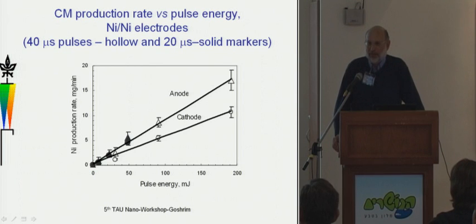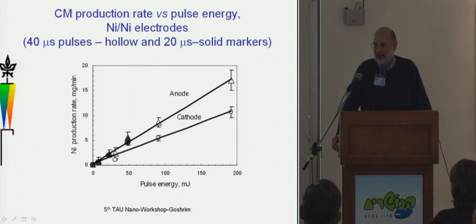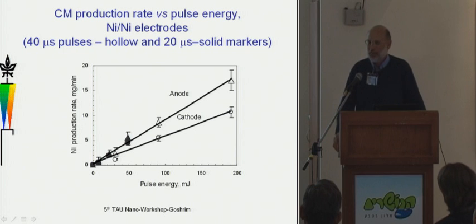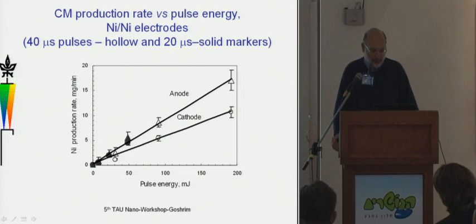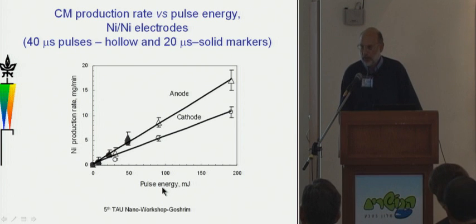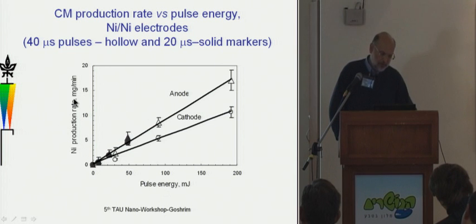We're concerned, being from the Faculty of Engineering, that eventually you want to do this in a factory, and therefore production rate and scalability are things that are important to us. So we've done a lot of work in measuring erosion rate and hence production rate of particles. And depending upon the pulse energy, in other words, how much energy you're storing in the capacitor, and the pulse repetition rate, this will control the erosion rate and therefore the production rate. And the scale here is in milligrams per minute.